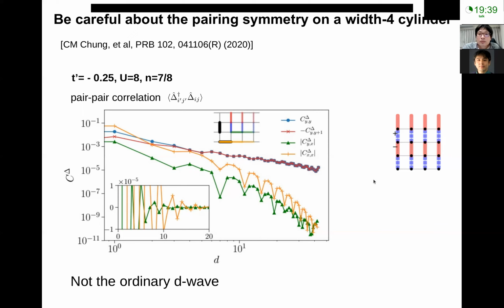If we consider the correlation of this black vertical bond to all the blue vertical bonds, it's shown by this blue curve. Then the correlation between this vertical black bond to all the red vertical bonds shows this red curve, with the correlation having a minus sign. So the correlation to the blue bond and to the red bond are perfectly symmetric, but they have different signs.